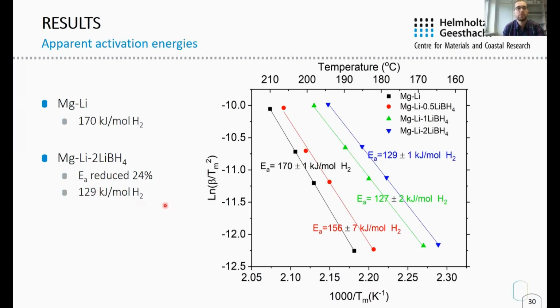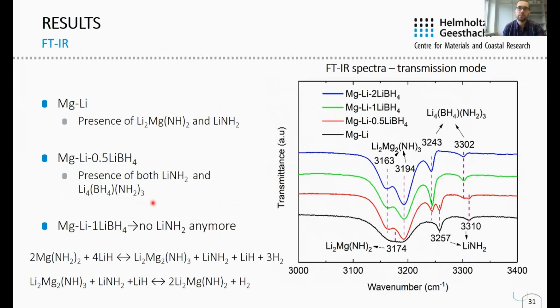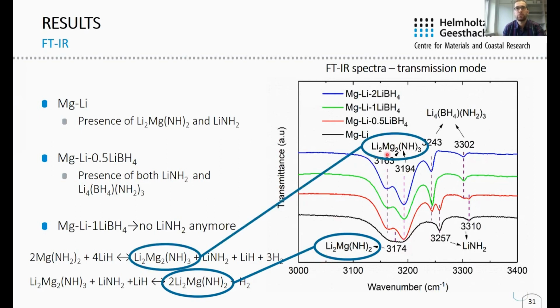To confirm this, I did the structural analysis using FTIR. FTIR measurements of the desorbed samples were done in transmission mode. As we see in this figure, for the pristine sample, N-H stretching vibrations of Li2Mg(NH)2 are positioned at 3174. Additionally, lithium amide is present. Different from the pristine sample, all lithium borohydride containing samples show Li2Mg2(NH)3. It is worthy to note that Li2Mg(NH)2 is the product of the second step, and Li2Mg2(NH)3 is the product of the first step of the reaction.